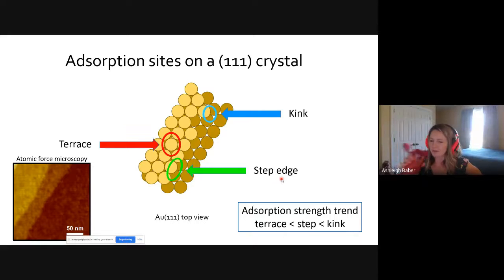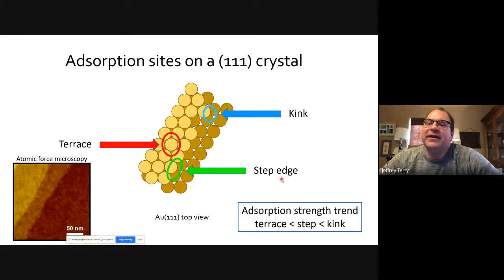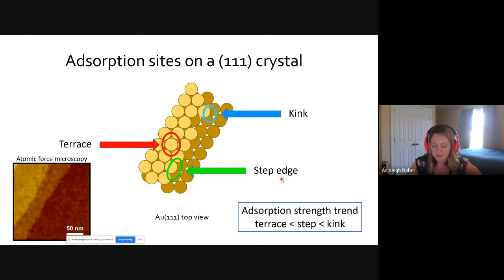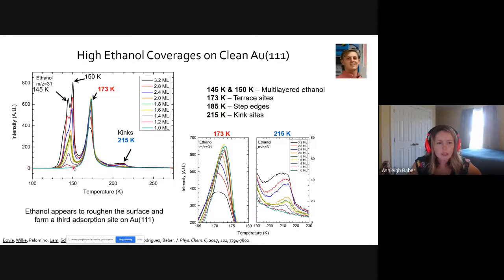No worries. How did you calculate the monolayer coverage? Yep. So the way that we do that is, if I just scoot back to here, you can see that there's this green peak here where we have one monolayer present. So basically what we're looking at is a saturation of that one monolayer peak. And then we go in through OriginPro and look at the area underneath that monolayer peak. And then we can compare that to some of these other coverages as well. Ethanol gets a little tricky, but we basically just look at the saturation of this terrace peak and take the area under that curve.